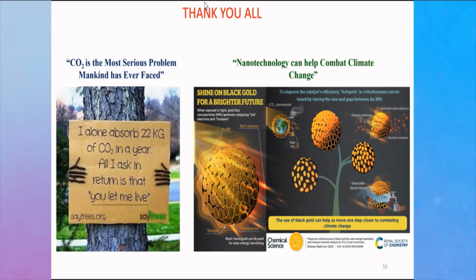Ashu Srivastav asked, how do you change the size of the nanoparticles? There are different ways. One is you change the template, and based on the template size, you get a different size of particle. You can also change the reaction temperature and reaction time, and you control the growth process. So if you don't let them grow, you get a smaller particle. You let them grow for a longer time, you get a bigger nanoparticle.